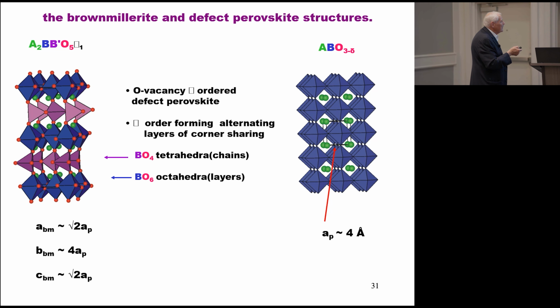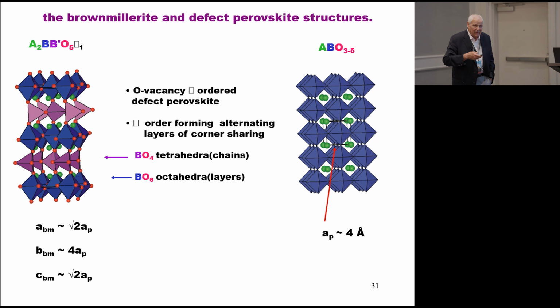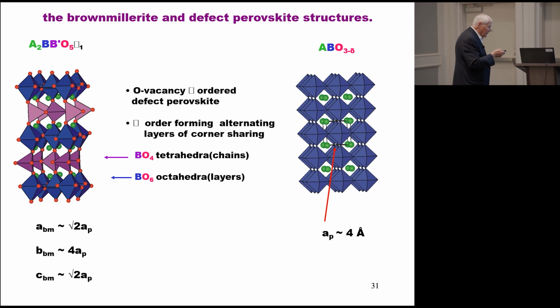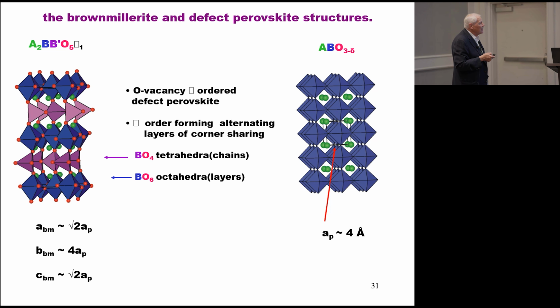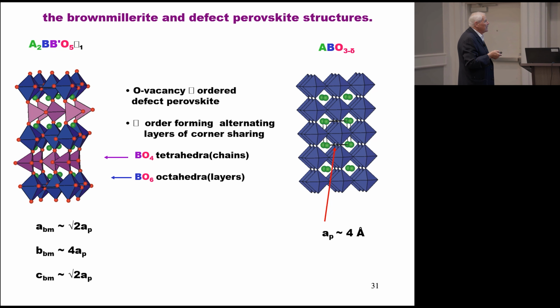Okay, well, when the A site is all calcium and half the B site is manganese, in any of these ratios, we get full oxygen vacancy ordering. And this leads us to something called the Brown-Millerite structure, which is shown on the left, in contrast to a random vacancy disordered perovskite on the right. The consequence of the vacancy ordering is that you get alternating layers of octahedrally coordinated B-site ions and tetrahedrally coordinated B-site ions. And this very large superlattice, if you like, is 8 times the volume of the primitive perovskite itself.